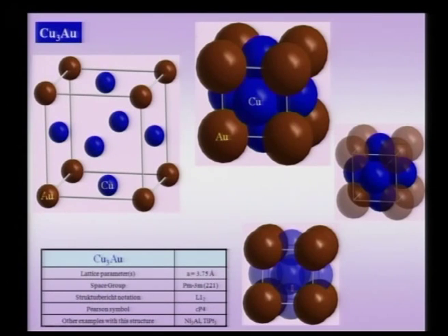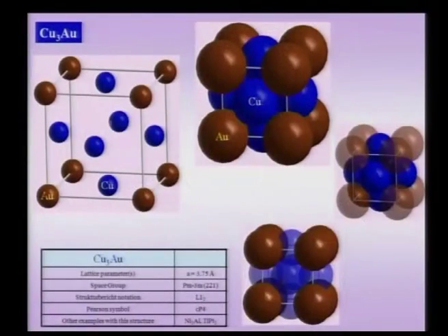Now, what is the crystal structure? This crystal structure is cubic and it has not lost its three-folds. As you can see, these body diagonals all have a three-fold axis, and in fact it has the highest symmetry for a cubic, and it's a primitive. It has 4/m 3bar 2/m kind of symmetry, and in the Strukturbericht notation, this is called an L12 symbol.